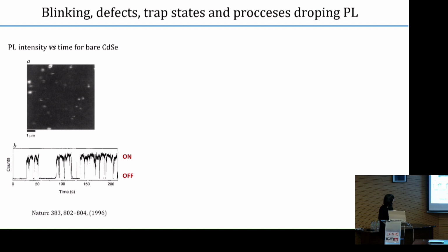So, I would like to highlight a couple of milestones that have been reported during the course of these years, which I think are very important for later understanding the applications of these quantum dots. One was reported by Brus, Alivisatos, and other co-authors in 1996. It's a property called the blinking of the nanocrystal, which means the intermittency in the emission of these nanocrystals. When you have an ensemble, you cannot distinguish this blinking effect. But when you study them individually, then you see this blinking effect, this intermittency in the photoluminescent response, giving rise to on-off states. Of course, this is bad for applications because your crystal cannot be in an off state if you want it to be a source of light.